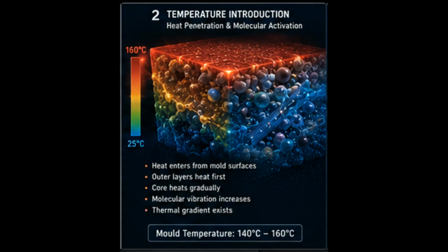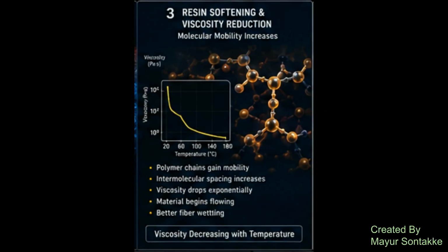Heat penetrates the material from the mold surfaces, activating the molecules. The outer layers heat first, and the core heats gradually, creating a thermal gradient. Mold temperatures typically range from 140 to 160 degrees Celsius. The heat causes the resin to soften, and its viscosity reduces. Polymer chains gain mobility, and intermolecular spacing increases. This exponential drop in viscosity allows the material to begin flowing, leading to better fiber wetting.